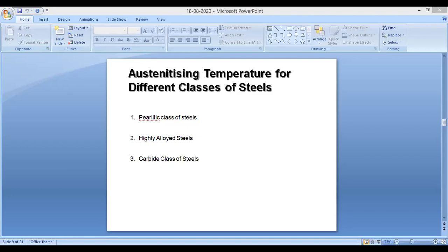If the temperature of austenitizing of hypereutectoid steels is increased, but still below ACm temperature, correspondingly increased amount of cementite is dissolved in austenite. Grain growth of austenite may occur as the cementite barriers to the motion of grain boundaries, essential for grain growth, have largely dissolved. On quenching, coarse grain martensite with a little amount of undissolved cementite and a large amount of retained austenite are obtained.